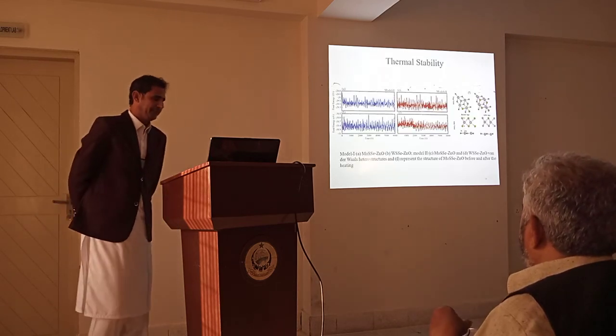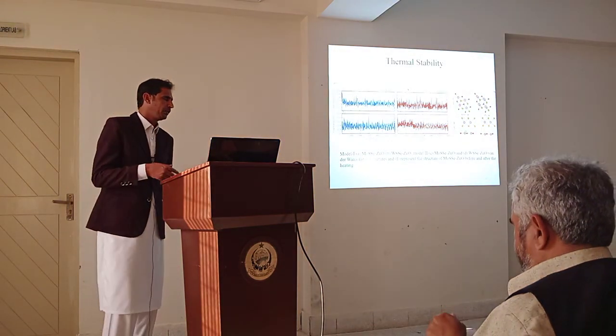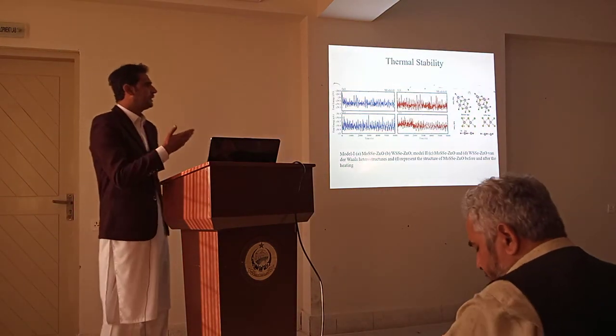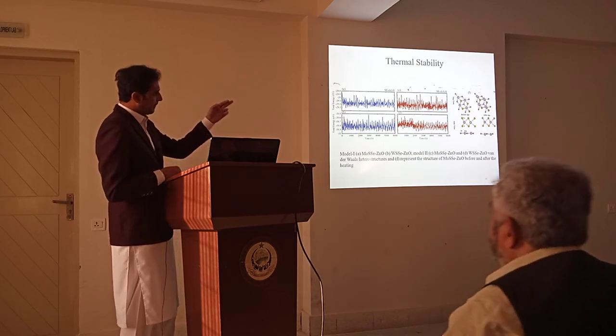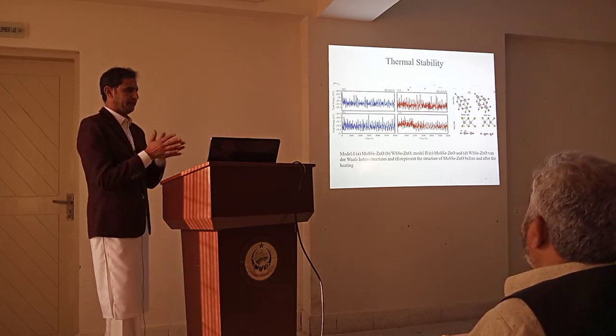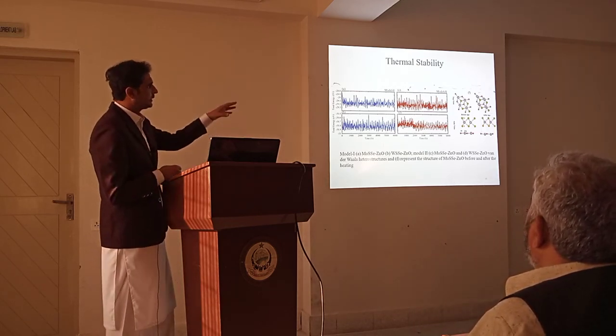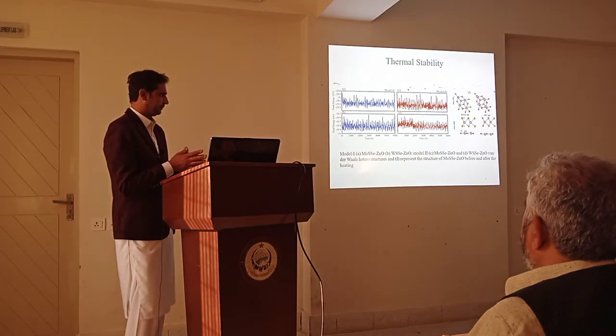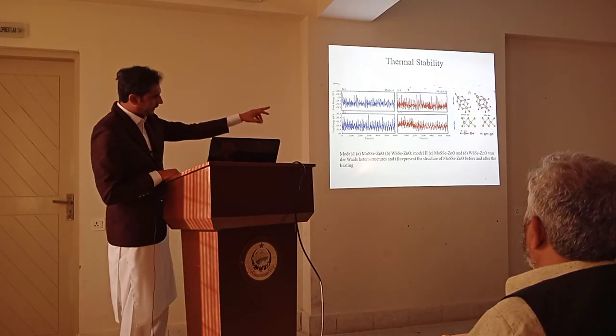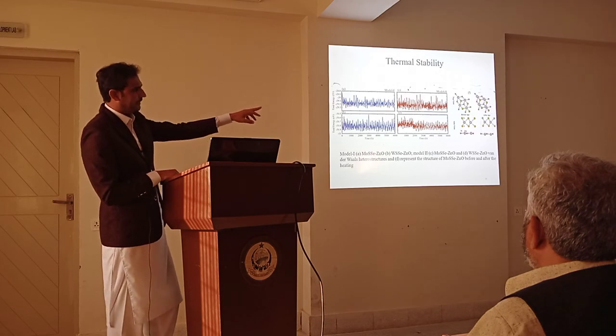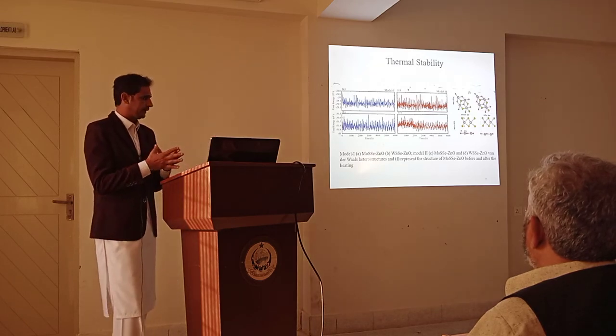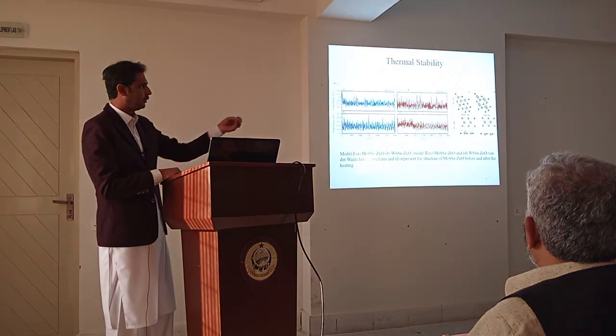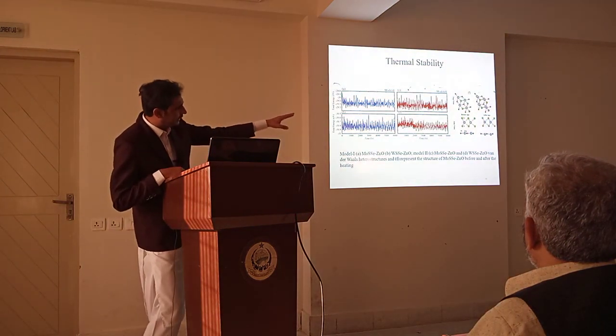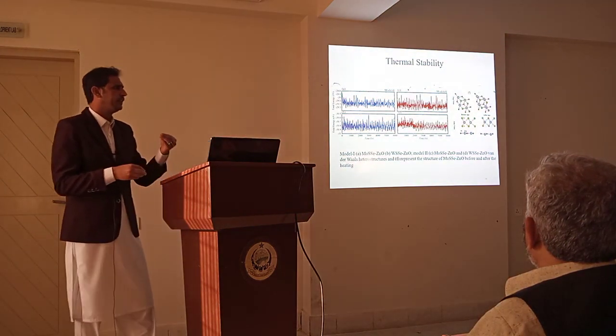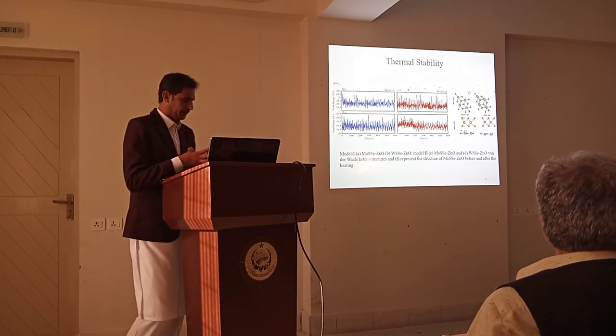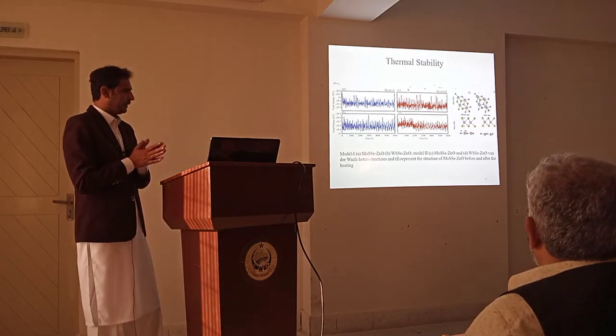Now to check that this system is thermally stable, we have calculated the thermal stability of this system. We can see here, along the z-axis, the fluctuation of energy by applying heat. We can see that this fluctuation is very small for all these systems. And the F represents the distortion of atoms, the distortion of the heterostructure or monolayer after stacking. We can see that there is no distortion, or the distortion is very small. That means that these heterostructures are thermally stable.